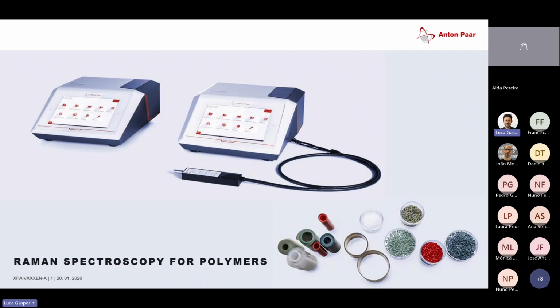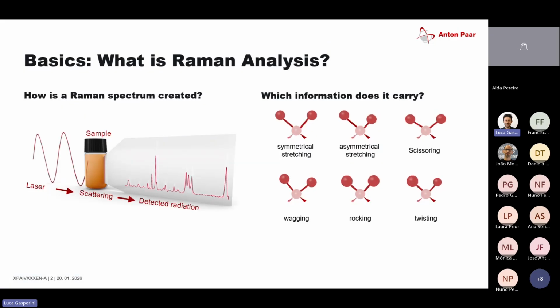So now we switch from FTIR to Raman. So obviously I start with the same thing. How does Raman work? Instead of an infrared light source, we're using a class 3 laser, which is in the visible to near infrared range. So I have a lot more power, and I do not measure the residual energy from the sample, but what I actually measure is the light scattering. So I take the laser, shoot it into an organic sample, and then I measure the energy change.